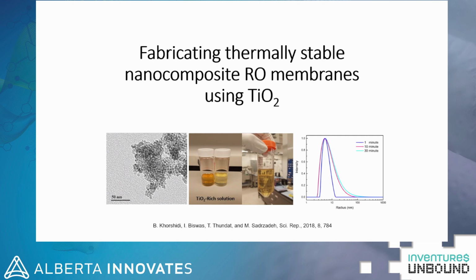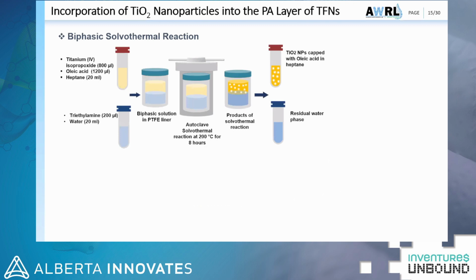So we provide a solution for this problem by simultaneous preparation and surface modification of TiO2 nanoparticles. As you can see here, our TEM and DLS, transmission electron microscopy and dynamic light scattering, characterization showed a monodispersed solution of TiO2 in heptane. The nanoparticle solution was transparent. This is a good sign that shows that the synthesis of small size TiO2 nanoparticles, around 10 nanometer, was successful. So how could we do this? By biphasic solvothermal reaction, to make oleic acid surface modified TiO2 nanoparticles in heptane. I recall that heptane is the organic solvent that we are using in our interfacial polymerization reaction to make the top layer of the TFC RO membrane.